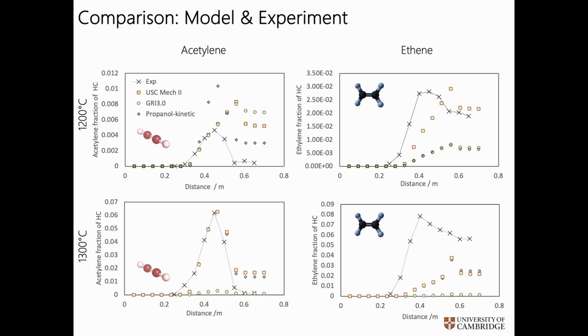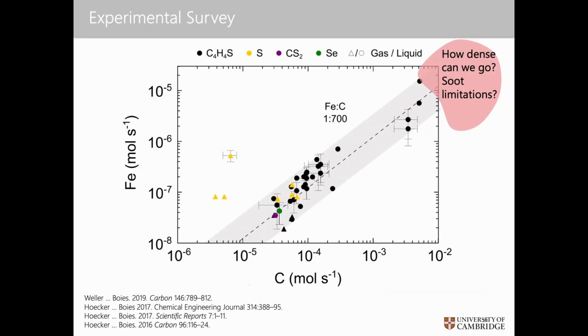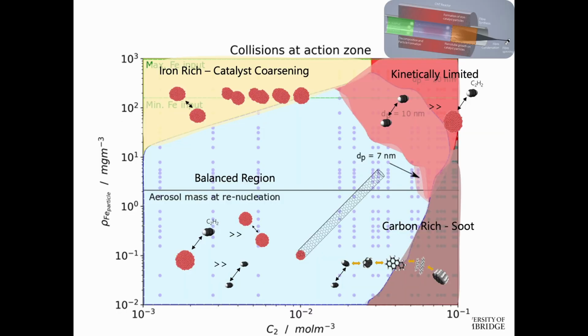But where we are really bad is describing ultimately some of the carbon nanotube growth rates. So if I take that same plot from before, with an iron and carbon axis, iron on the y-axis, carbon on the x-axis, and I look at what limits us: as we start putting in lots of iron, the iron particles basically collide together too much and grow too big. We need these particles to be nanoparticles. If they get to be too largish of nanoparticles or even micron-sized particles, they don't grow nanotubes anymore. On the other end, if we put in too much carbon, we get soot production pathways. And that's not desirable either.